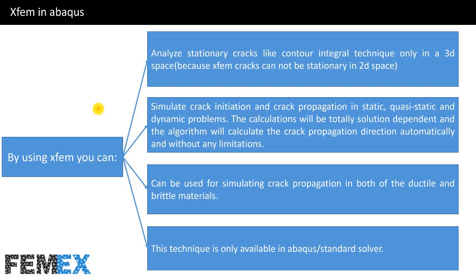By using XFEM, you can simulate crack initiation and crack propagation in static, quasi-static, and dynamic problems. The calculations will be totally solution-dependent, and the algorithm will calculate the crack propagation direction automatically and without any limitation. It means that there is no need for defining the direction of the crack propagation or the plane of crack propagation. The XFEM algorithm will calculate this direction automatically.